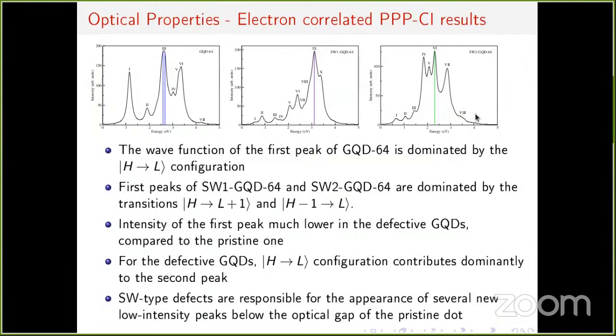But the most dramatic changes occur when you look at the optical absorption spectrum. On the left panel, we have the optical absorption spectrum of the pristine dot. In the middle, we have that of the dot with the Stone-Wales defect at the edge. And on the right panel, we have that of the dot with the Stone-Wales defect in the middle. First, a few features. For the pristine dot, the HOMO to LUMO transition defines the optical gap, but a dramatic change occurs for the defective quantum dots: HOMO to LUMO is no longer the lowest state, rather H to L+1 and H-1 to L become the lowest states. So the defect introduces subtle changes in the system.